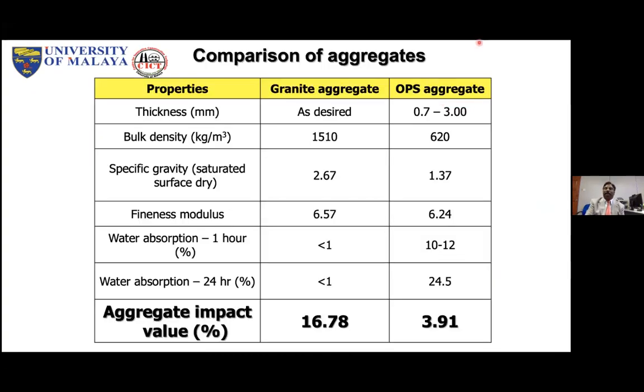I hope he's around to listen to my answer. If you look at this aggregate impact value, Sharma, it is almost 16% for the normal weight aggregate. But for this lightweight aggregate, it is less than 4%. Impact means we drop a hammer of certain weight from about 500 mm height. After a certain number of blows, you measure the amount of crushed particles passing through certain sieves. That's called the aggregate impact value.